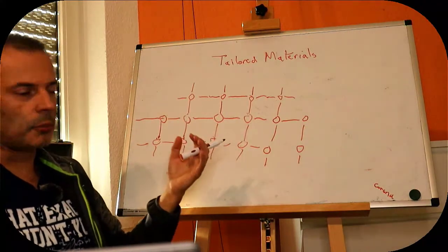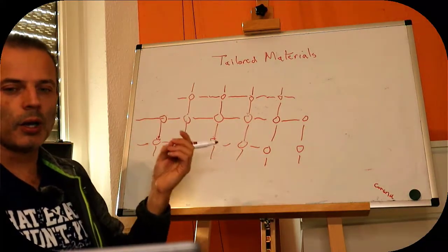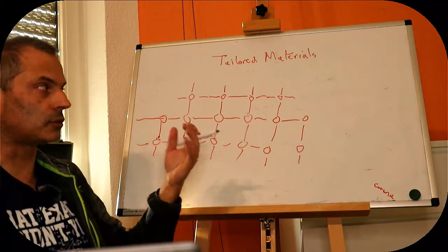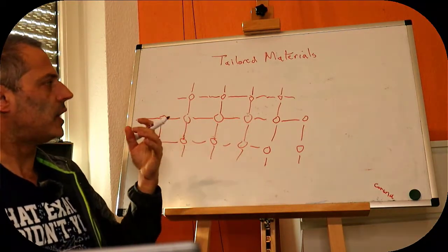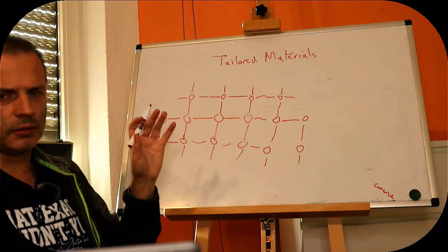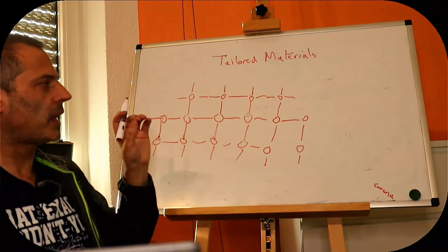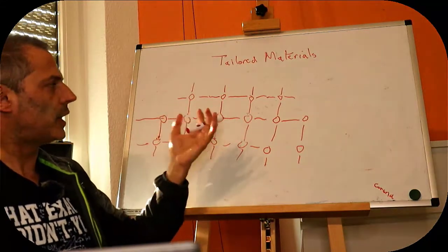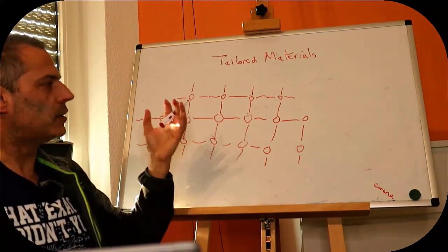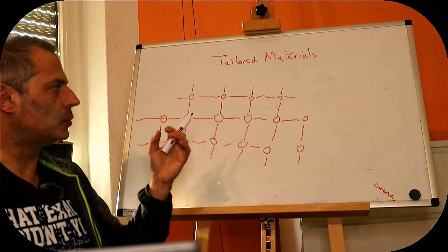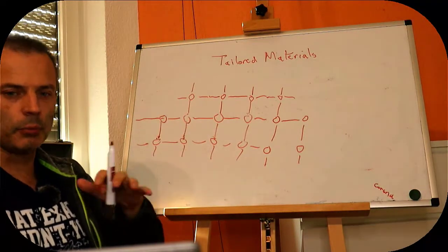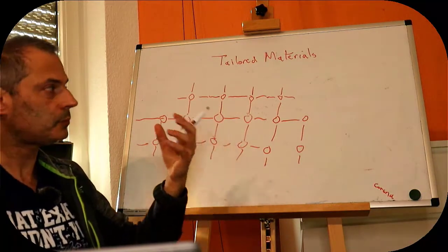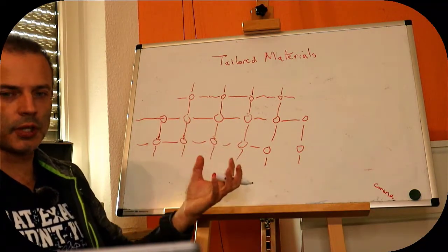The interesting thing about this is if we apply atoms at a constant rate or with a constant amount of energy, and they're coming in and they can leave again, then the rate of deposition goes down every time we finish a layer for a little bit until we start the next one, because it requires more energy to start the next layer.